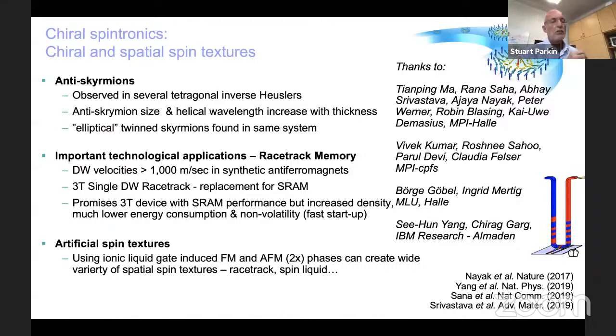And then finally, just briefly at the end, something we're doing more recently is to create artificial spin textures by using oxide materials in which we locally add or subtract oxygen. And we can do this on approximately the 15 nanometer length scale to create boundaries that are 5 nanometers wide. I think this has a lot of interesting potential to create spin liquids, racetracks, and other types of structures, and maybe chiral spin structures as well.